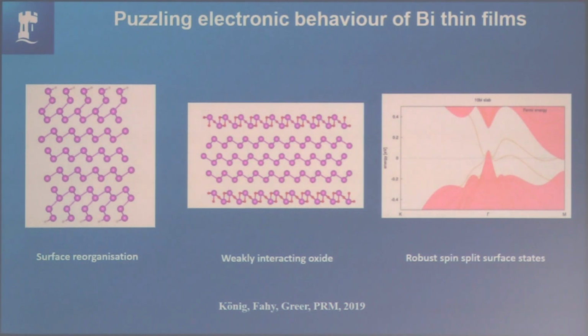It would not gate. You get little wiggles in the current, but actually it just would not gate. We tried different oxides. We tried many, many different things. Usually if you have something like that, you think, oh, I have a very poor interface. There's charges at the interface. The gate can't get down to control the channel.